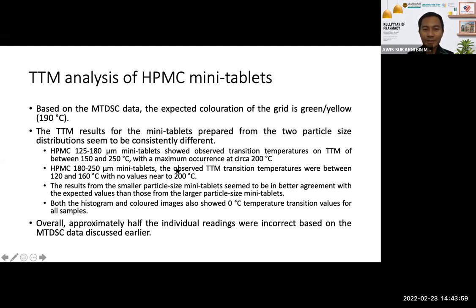For the bigger particle size, actually I didn't put the diagram here, but the temperature range is between 120 and 160 degrees, with no value near 200 degrees. So the result shows that the smaller particle size is in better agreement with the expected value, but still